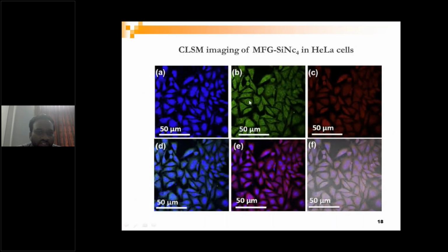Here you can see A is the control stained with DAPI, which reflects the blue color, and B is the green emission from MFG alone, because we just tagged it with a fluorescent label. C is the red channel corresponding to SiNC4, because it generates a red color. D is the combination of A and B, and E is the combination of B and C, whereas F is the combination of all. This means the fluorescence emission is purely from the nanomaterial, not from any other background emissions. From this slide we can conclude that the MFG-SiNc4 has been internalized into the cells through non-targeting pathways.